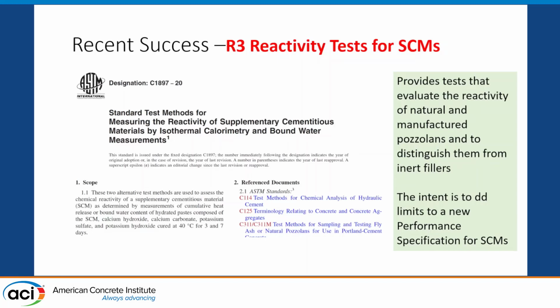How do you tell? A lot of the specs we have, like C618 for fly ash and natural pozzolans, use a strength activity test that, although it's okay with fly ash because we have a history of using fly ash, we sort of know what it does. I can take ground sand and make it pass the strength activity test in C618. That's not a very ringing endorsement for endorsing the reactivity of it.